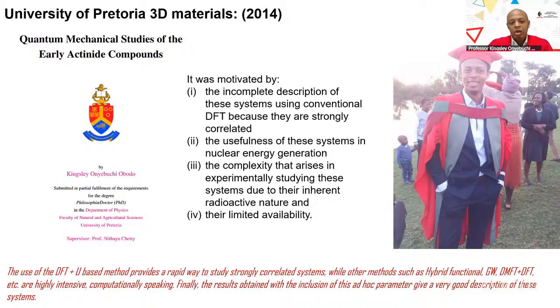It was motivated first by the incomplete description of these actinide systems using the conventional DFT approach because they are strongly correlated. And I also mentioned that these systems can be useful in nuclear generation, and they are quite expensive, so they have limited availability. So we can't just go and get nuclear materials and start working with them. And they're also very complicated. This is part of the reason why we looked at this. But some of the key findings from my PhD is that the use of the DFT plus U-based method provides a rapid way to study strongly correlated systems, while other methods such as hybrid functionals, DMFT plus DFT, etc., are computationally intensive. And the results that we obtained from the inclusion of this ad hoc parameter gave us a very good description of the systems of interest.